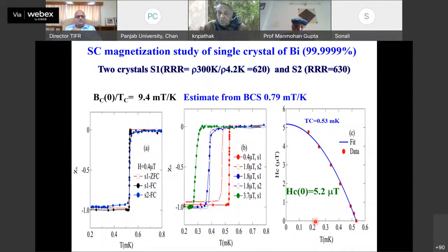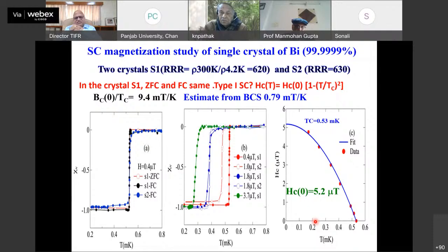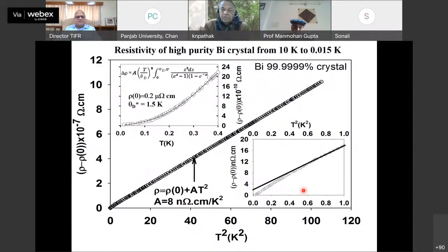And then we decided to look for 2 crystals of bismuth with extremely large residual resistivity ratio. The residual resistivity ratio tells you how good the quality of the crystal is. So it's comparable to the best available which we have grown, the 620 RRR and 630. And the important part is this discovery of superconductivity. You see that field cool and zero field cool show that it's something like a type 1 superconductor. And when you have a magnetic field, zero field is this. As you apply more and more magnetic field, the superconducting transition gets suppressed, as expected for the phenomenon of superconductivity. And you see a graph like this, where the critical field, which we estimated to be about 5.2 microtesla. So if you do this measurement without shielding, Earth's magnetic field is about 40 to 50 microtesla, which will just simply kill the superconductivity. You are not going to see this.